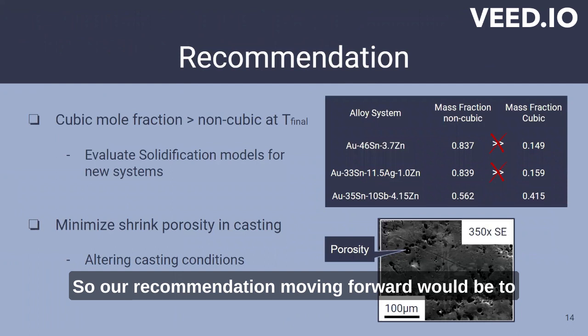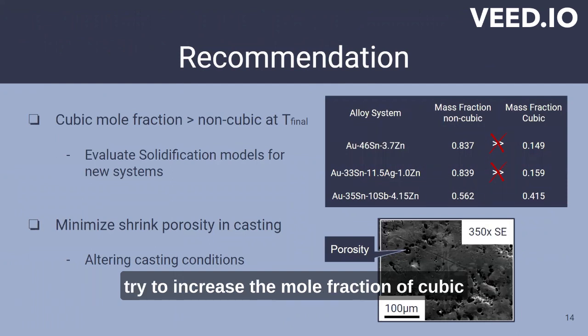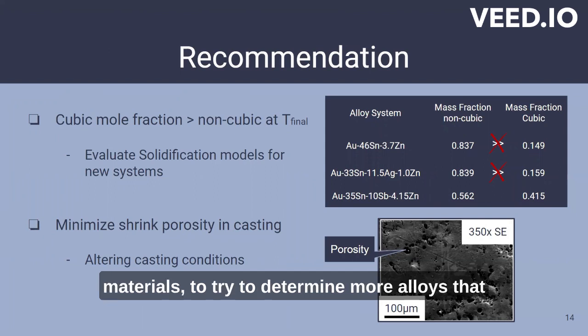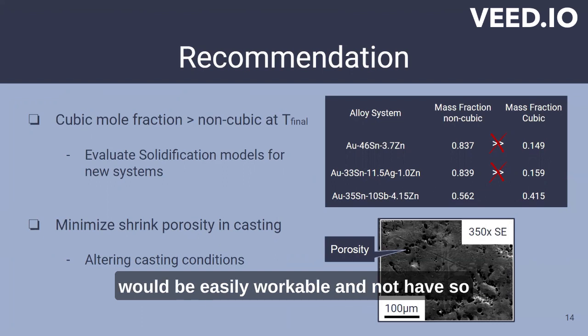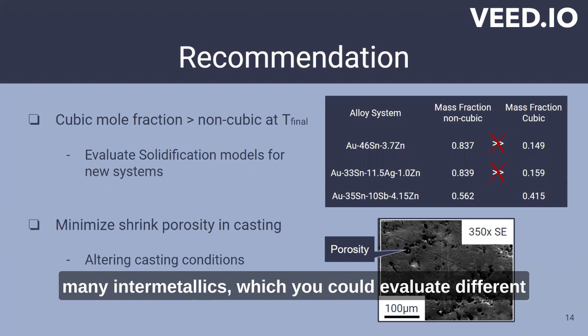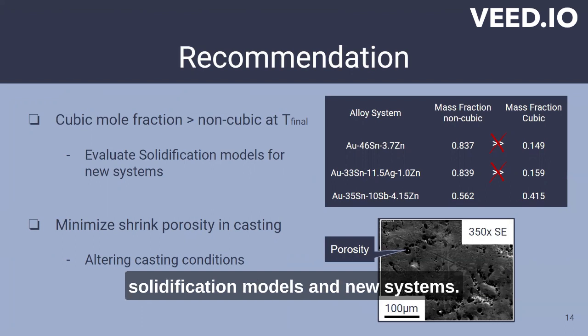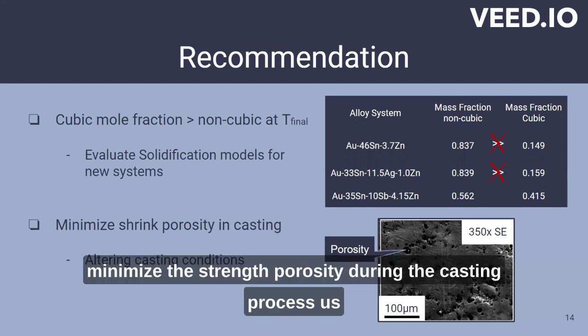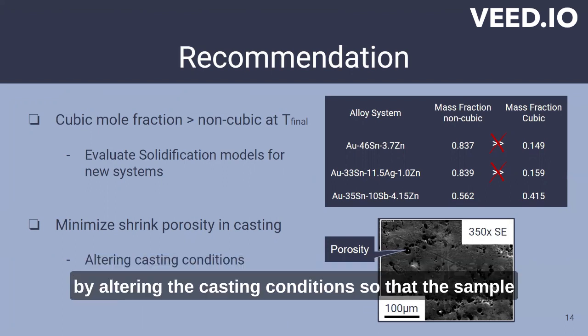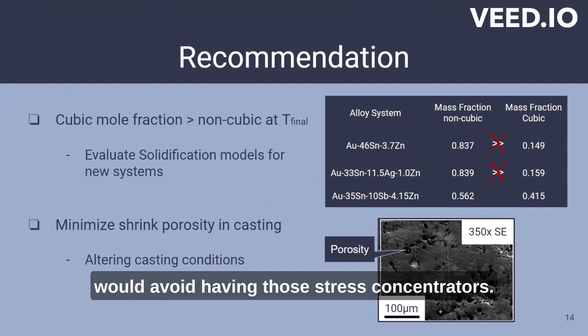So our recommendation moving forward would be to try to increase the mole fraction of cubic materials to try to determine more alloys that would be easily workable and not have so many intermetallics, which you could evaluate with different solidification models and new systems. And then another thing to do would be to minimize the shrink porosity during the casting process by altering the casting conditions so that the sample would avoid having those stress concentrators.